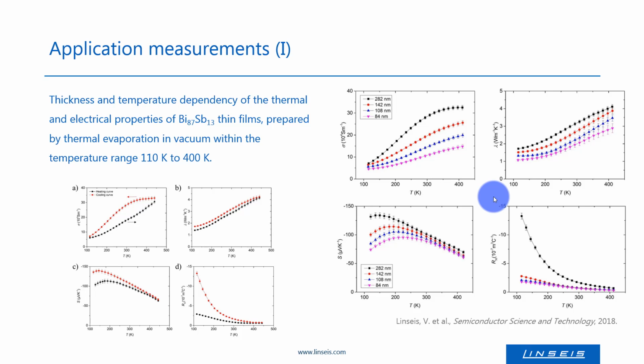In addition, the impact of thermal annealing on the transport property was shown, as a thermal cycle was measured. If you are interested in more details, the study has been published in the Journal of Semiconductor Science and Technology, where a lot of further findings like thickness dependencies and the influence of annealing on the thermoelectric films are presented.